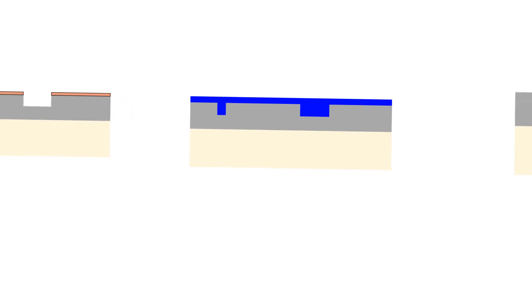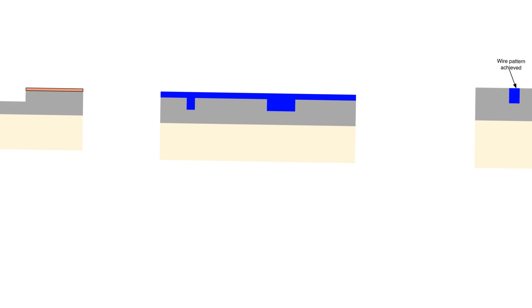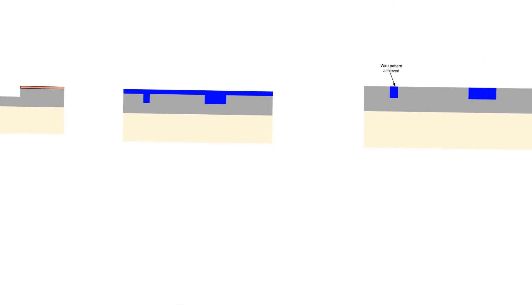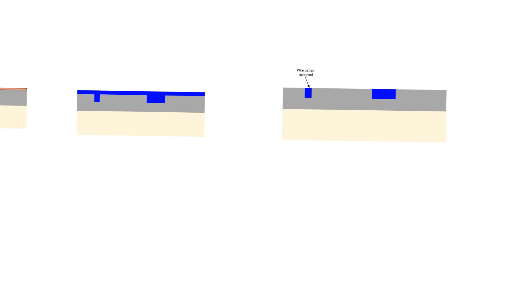Then we use PVD to deposit copper on top of the wafer. We have to cover it in a very thick layer of copper so that we overflow the trenches that we create. So we have to overfill and overfill comfortably. Otherwise, we might create unwanted opens or shorts. Then we use CMP and CMP will polish down the wafer until we reach the surface of silicon dioxide. CMP can actually do this and it can stop at a certain material. In this case, we will stop at the surface of glass or silicon dioxide. This leaves the metal wires that we created only in the trenches and thus gives us the traces that we want.